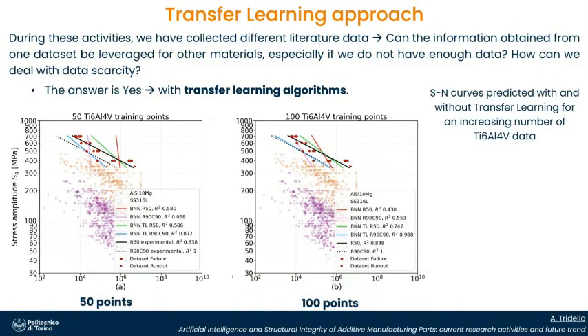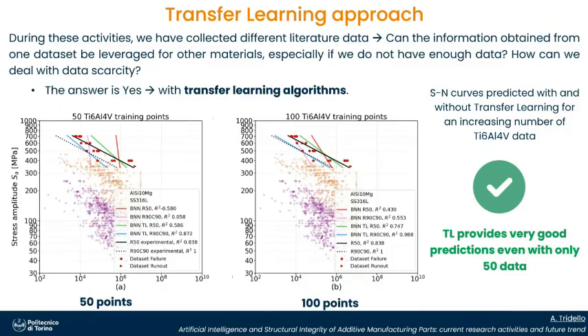And here you can see the same things. For 50 data, the estimated curve with only the data for the titanium alloy is not good. On the other hand, the curves after transfer learning are quite good, and with 100 data, the situation is better, and we have a very good prediction. So in this case, we have exploited the relationship properly. And to conclude this activity, transfer learning provides very good prediction even with only 50 data.